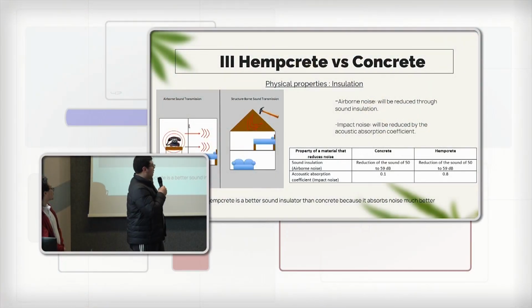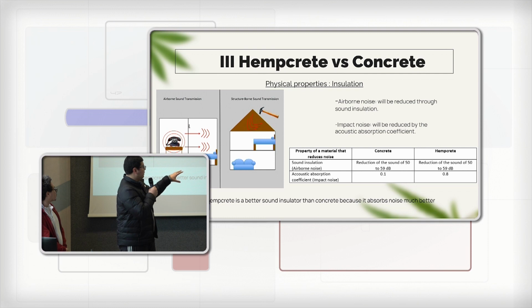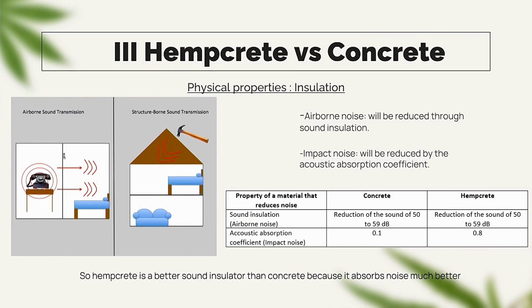As you see, the reduction of the sound for the two materials is the same, but the coefficient is 0.1 for concrete and 0.8 for hempcrete. So hempcrete is much better for sound insulation.